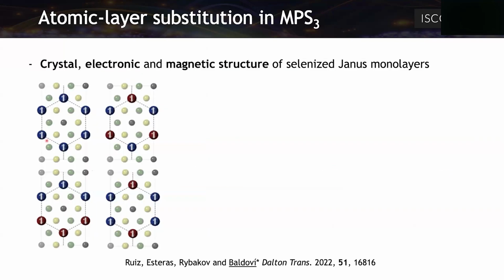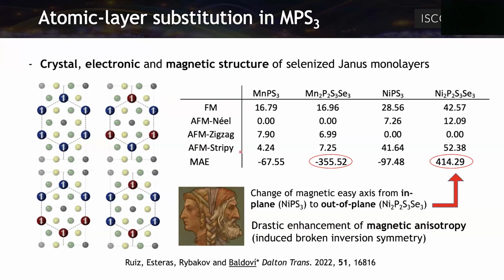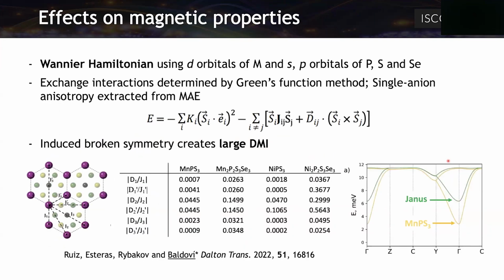So regarding the magnetic order, we are getting very similar results, but we are increasing the magnetic anisotropy energy. And this is what happens in the case of the nickel, that we are changing the sign. This means that we are also making the spins out of plane in the case of the nickel when we are doping with a Janus structure, and we are enhancing these Dzyaloshinskii-Moriya interactions, and this is making a big effect on the magnon dispersion for the Janus. Then,